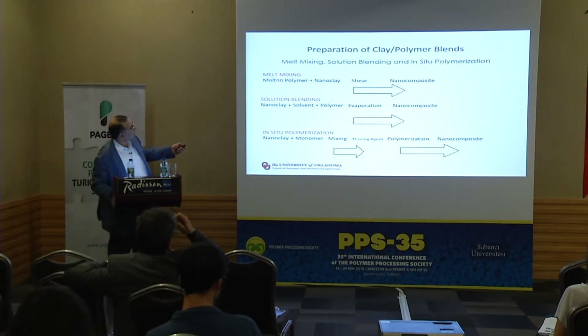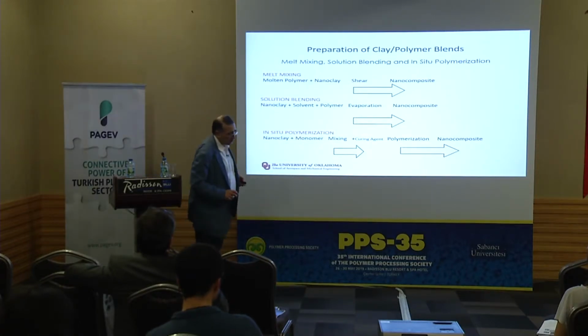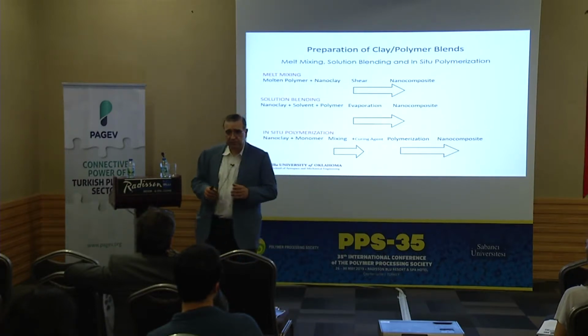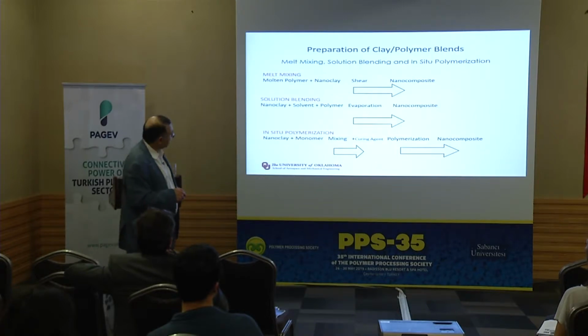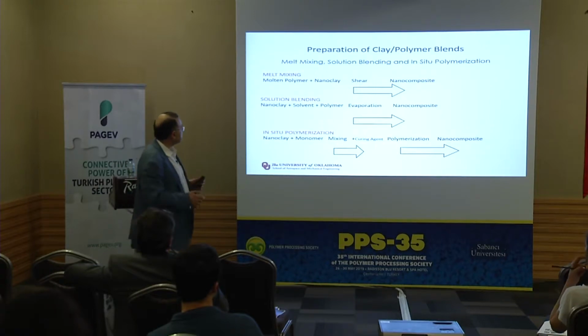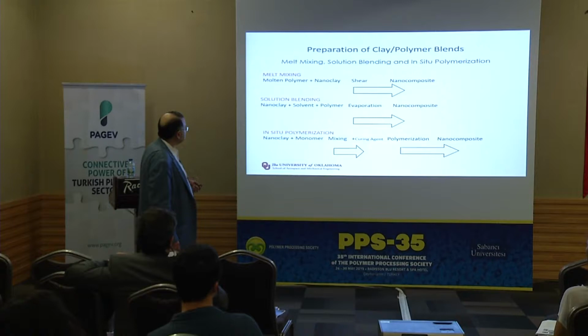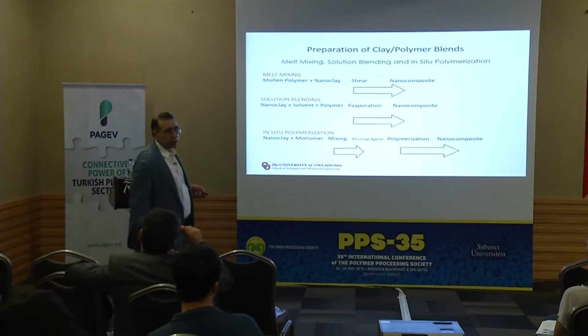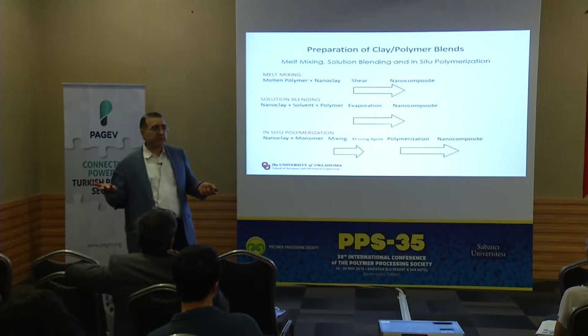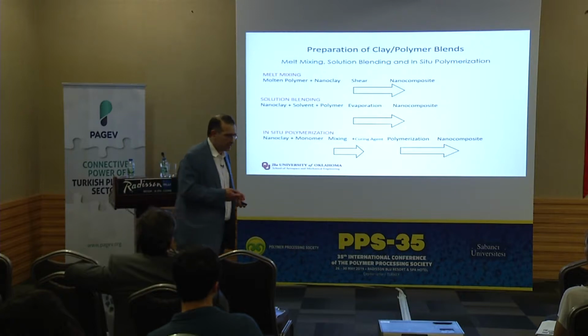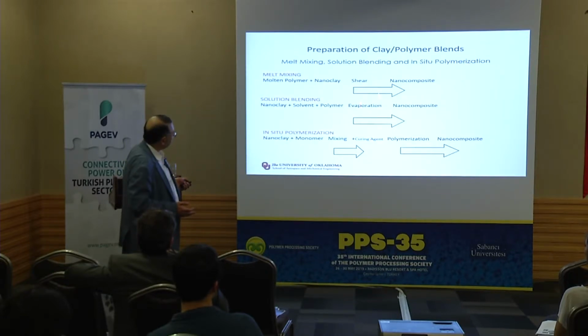So the processing ways are melt mixing, solution blending, and in situ polymerization. Primarily, you have the molten polymer, you have the nano clay, and in melt mixing, you apply shear, usually high shear. So you really have different blending methods and shearing methods. If you can apply high shear, you disperse the clay better. Of course, it depends on the viscosity of your polymer and so on. In solution blending, you have a solvent, so you dilute the polymer, so the polymer is less viscous, then it is easier to mix, right? And then you need to get rid of the solvent in one way or another. Sometimes people use different types of alcohols and acetone and so on, but these are more at the research level. People are trying.